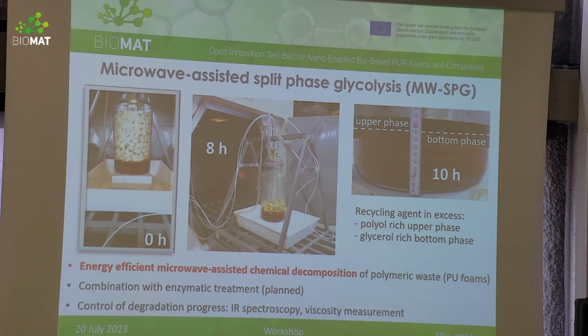In the middle, we see first the progress of reaction. After some hours, we have here a 30-liter reactor. We have installed a stirrer inside the reactor, which is operated by a motor, a pneumatic motor. We have to use it in the environment of the microwave oven. We can flood the reactor with nitrogen as inert gas. And because typically we heat up the recycling agent to its boiling point, we have also a reflux condenser on top of the reactor, just to be able to do the boiling at the boiling point of the recycling agent.